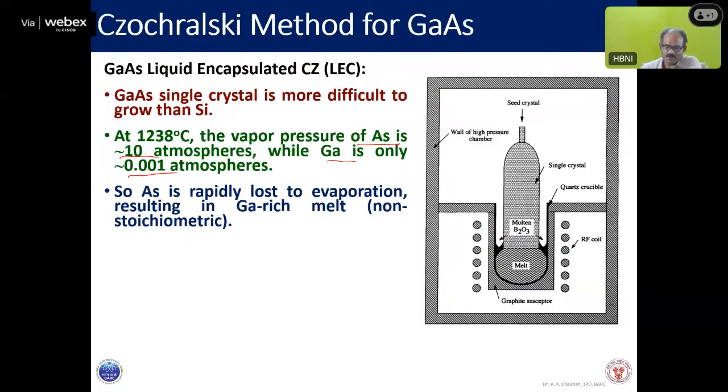For this, you have a slight modification called the liquid encapsulated Czochralski method, in which you place boron oxide with the material.